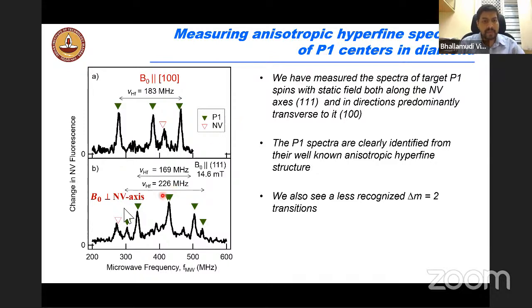And we again have been able to do this spectroscopy where we are driving at the P1 resonance, not at the NV resonance. And we are able to see the hyperfine structure of the P1 center. And we can verify that this is indeed the P1 center by looking at the hyperfine spectrum. And so we have been able to do this under different conditions, whether the magnetic field is parallel to the NV centers, or it could be predominantly perpendicular, which is along the 100 direction, not exactly transverse, but more or less transverse to the NV center.